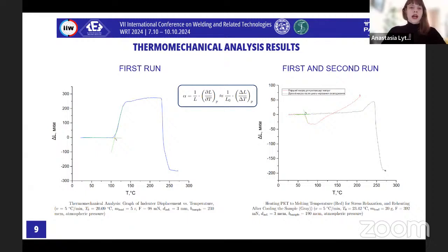And also, I conducted a second experiment, and as shown on the graph on the right, there are two steps of the experiment because it allows relaxation of residual stresses. So the sample is firstly heated to 210 degrees, then cooled to room temperature and reheated to the melting point. So in this graph, the red curve represents the initial heating for stress relaxation. That's the purpose why we're doing that. And the gray curve represents the second heating following the heating and cooling cycle.